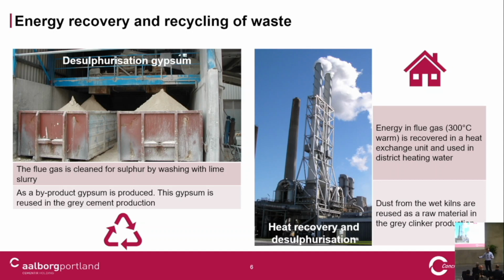At first glance it would look bad. And we produce gypsum which is reused in our grey cement, recover the heat used for domestic heating, and also the dust from the wet kiln with all those volatiles - high in alkali, high in sulfate, high in chloride - is also reused in our process.